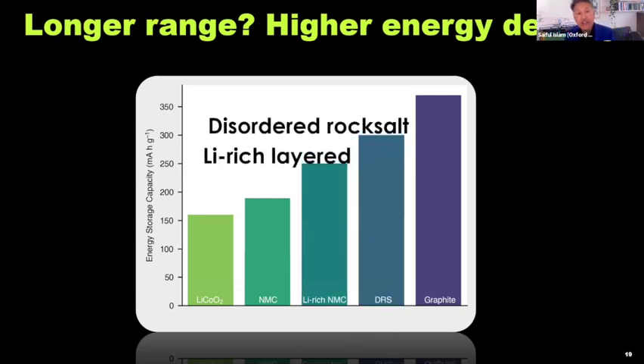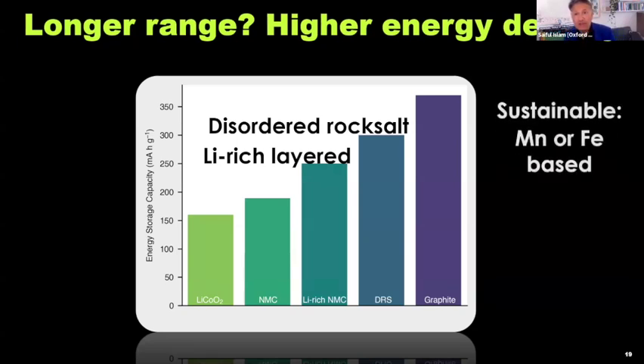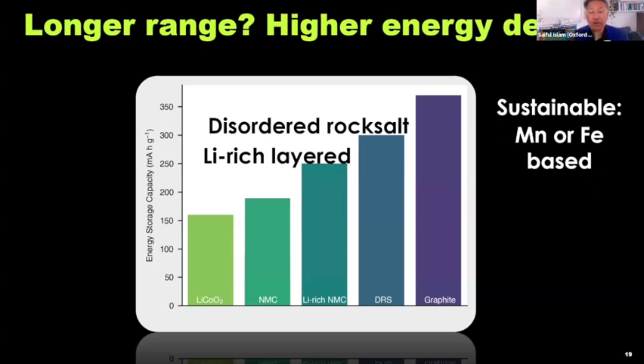And we're looking at these lithium-rich layered materials and lithium-rich disordered rock salt materials, which, as you can see, have much higher energy density and getting towards graphite. They also have the advantage of being more sustainable because they're mainly made up of manganese or iron. There are issues to do with cobalt and nickel in terms of abundance, cost, and their mining.